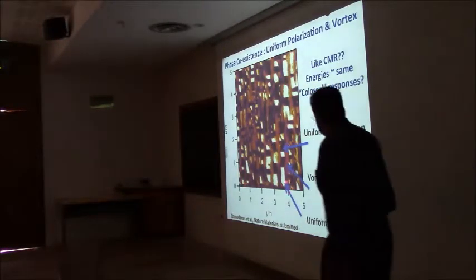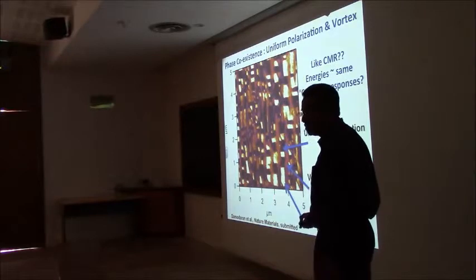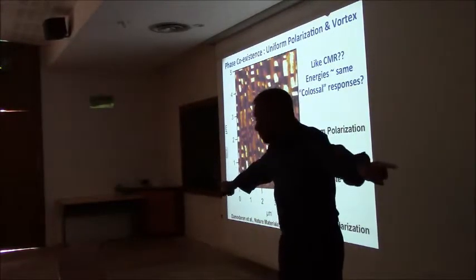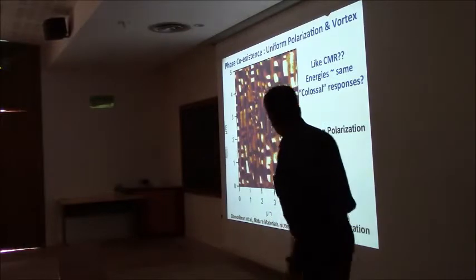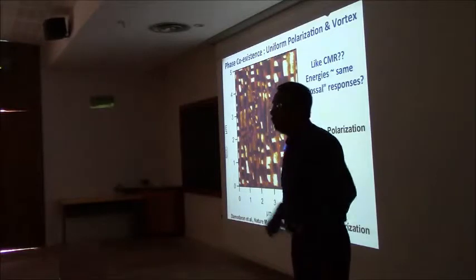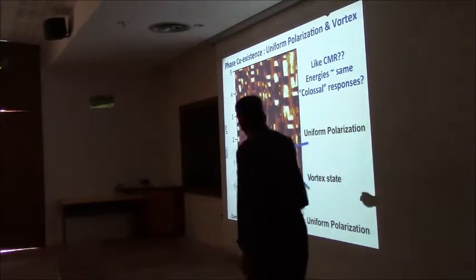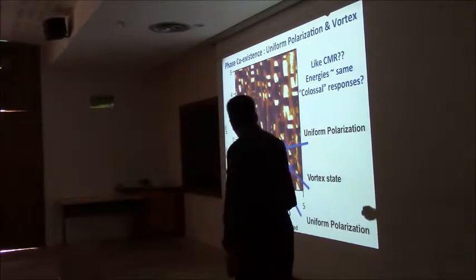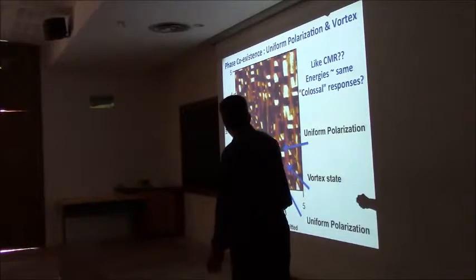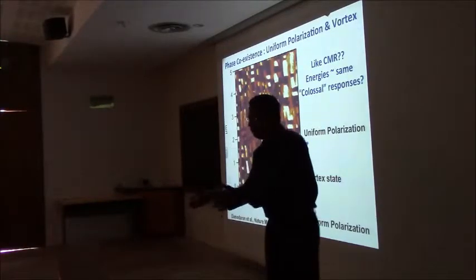So these regions, which look like a snake surface, have in-plane polarization components like this. Uniform polarization this way, uniform this way. In between them, you have these regions which are essentially neutral contrast. Those are the vortex regions. And the vortices, keep in mind that this next scale is microns. This is about 200, 300 nanometers. The vortices are running this way. So there's a whole array of vortices.